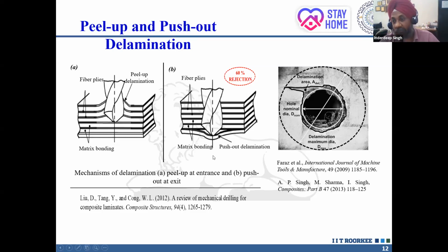But the major challenge is the push down type of delamination, when the drill tends to exit from the laminate. The bottom layers try to open up under the thrust force that is exerted by the drill on the laminate. Therefore, once this delamination takes place, the bottom layers tend to peel down or push down. Push down delamination is reported; 60% of the holes are rejected.